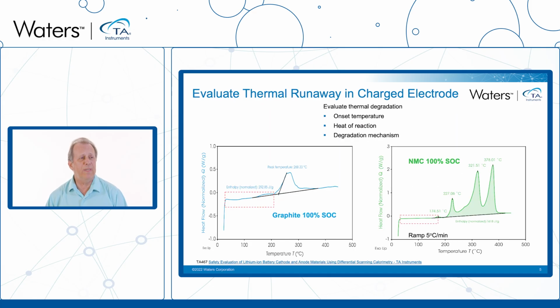So moving on to some data here, I'm going to show a comparison between graphite and what's called NMC. The NMC is a cathode material. It's lithium, nickel, manganese, cobalt oxide. And then we have, as I say, the graphite on the left-hand side. Both of these materials were part of a battery pack that was charged and discharged several times and then finally left in a 100% charged state.